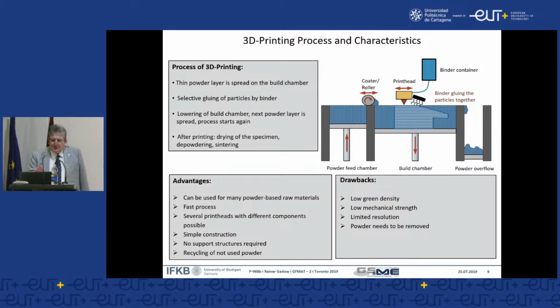So this, the central part of the apparatus is called the build chamber, and as I mentioned before, layer by layer, we introduce a perfect even powder layer, and then the process starts again. If the geometry of the component is completed, it is carefully taken out, the excess powder is separated, and then the part goes, in analogy to what I have said before, to thermal treatment, careful at the beginning, and then to the sintering operation, so that we have finally the component that is ready for surgery, for medical application.